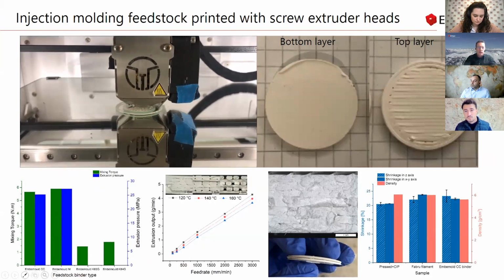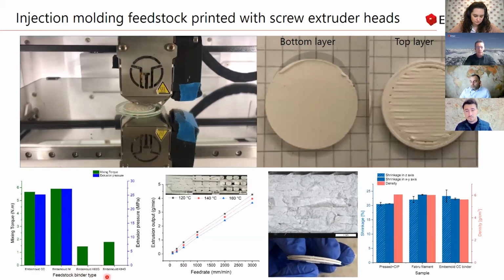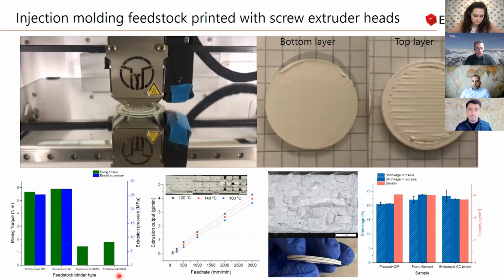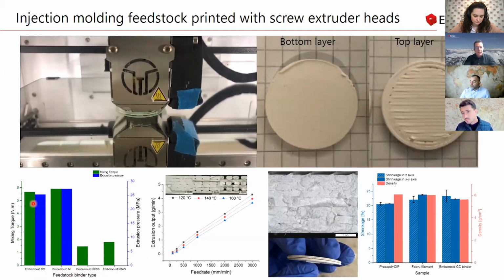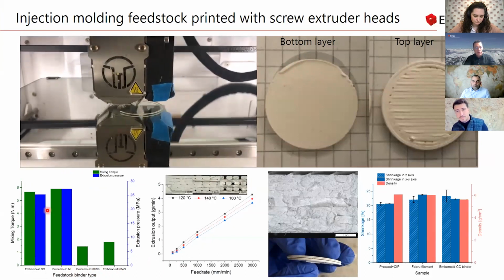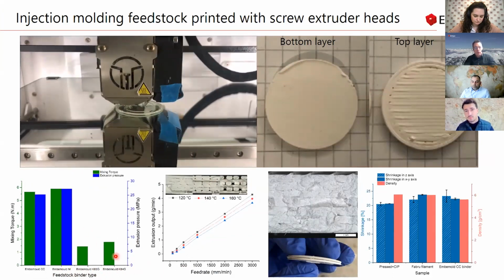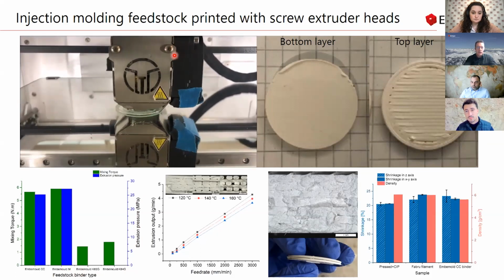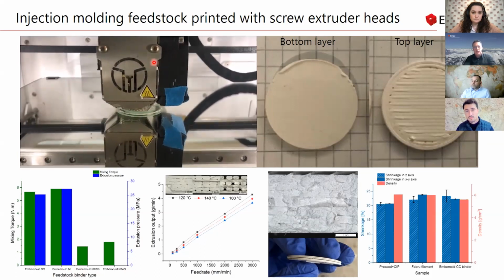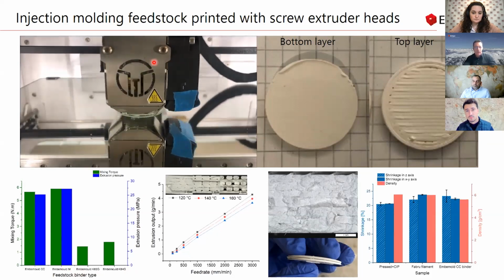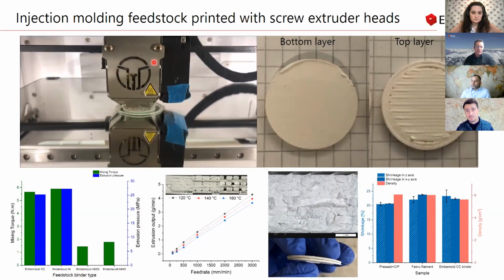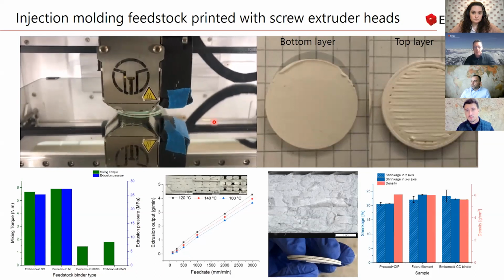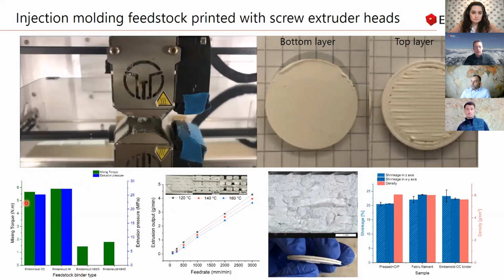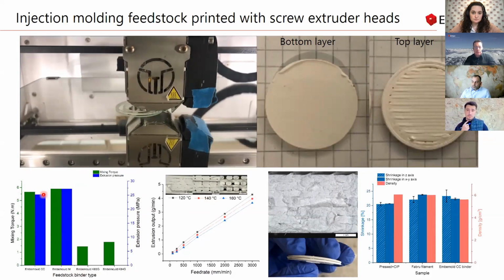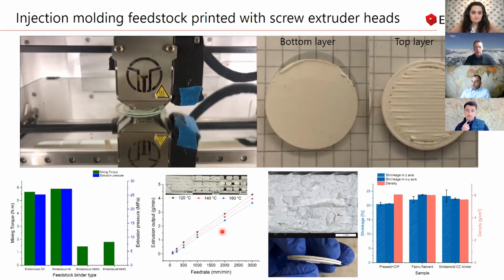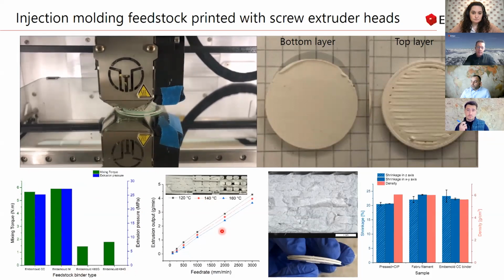But we used here 4 different binder systems, and we made a ceramic feedstock out of it. And you can see that 2 of them were able to print. The other 2 have waxes inside. So that means when we start to print with these print heads, we have a phase separation and the waxes are separated from the feedstock. However, interesting for these 2 feedstocks which we made by ourselves with a commercial injection molding binder system.